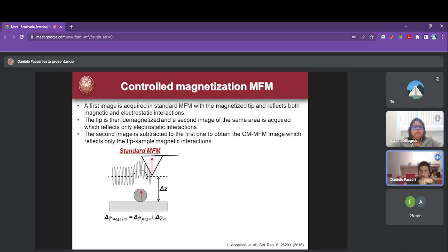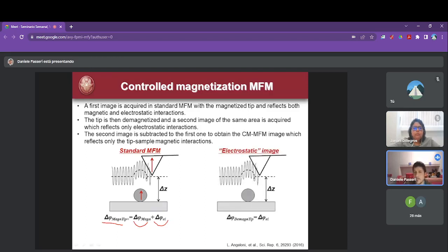of the tip. So the idea was, first let me measure a standard magnetic force microscopy. Standard magnetic force microscopy gives you a signal which is the real magnetic signal plus the electrostatic signal. Then we apply the magnetic field corresponding to the remanent coercivity. We switch it off, and so we demagnetize the tip. And we repeat the scanning. As we have switched off the magnetization, the signal is only the electrostatic one. And so you can simply subtract the second from the first, and you obtain the pure magnetization signal.